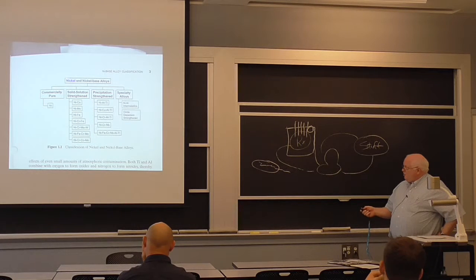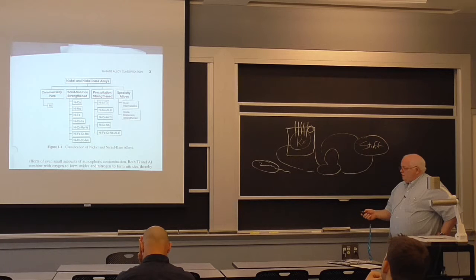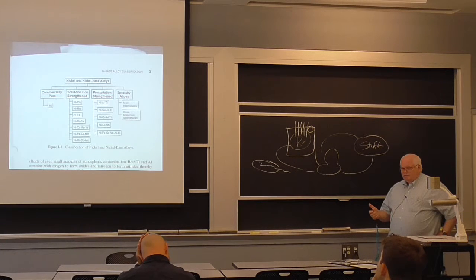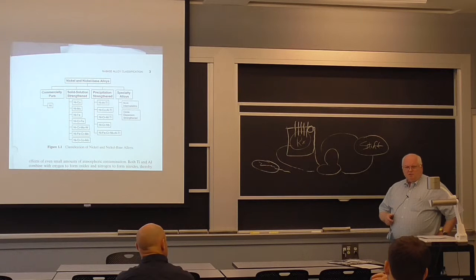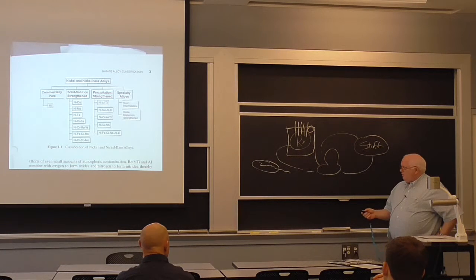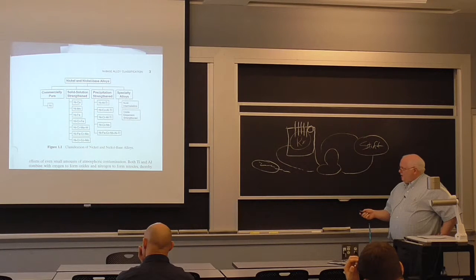Anyway, so nickel and nickel-based alloys. The problem with nickel alloys is they're expensive. You're talking, I don't remember what my numbers were, but I think it's $6.50 a pound for nickel, just as pure nickel. And we use commercially pure nickel for some situations, but like most pure metals, it doesn't have very high strength. So we can strengthen it by adding copper or molybdenum or iron or chrome and iron.